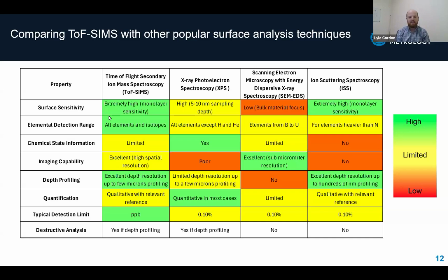And then SEM EDS can provide more bulk information to the micron length scale, and it can offer really quick and simple mapping, as well as giving you complementary SEM information of the microstructure of the sample. And then another really unique technique that compares as well is ISS, otherwise known as low energy ion scattering. This enables even higher depth resolution, but effectively no lateral resolution. It's a few millimeters. But what this allows you to do is characterize just the topmost layer of a sample. And this is really useful for very thin ALD films where you're trying to see if they're conformal.